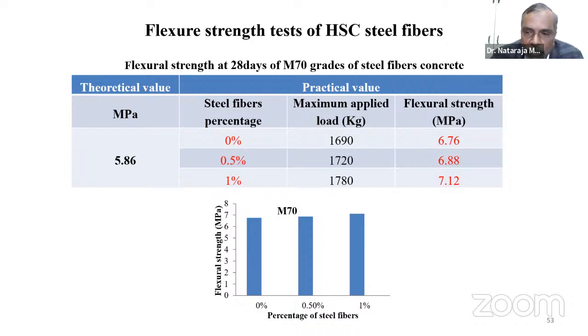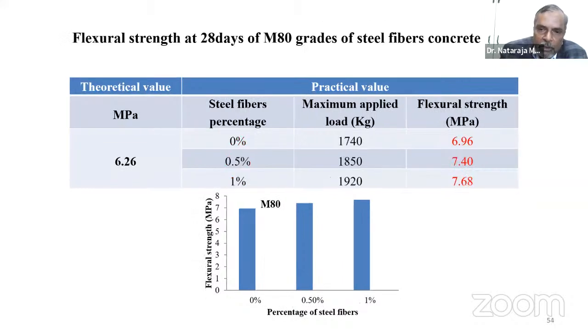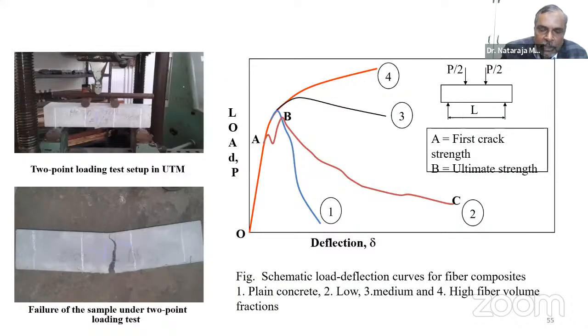But in addition to the flexural strength increase, we are getting many of the other improvements, especially from the point of view of energy absorption capacity. If that is the requirement, I suggest you put the steel fiber. Otherwise, don't put the steel fiber just to get some increase in the compressive strength or the flexural strength. And this is the relation you all need to appreciate.